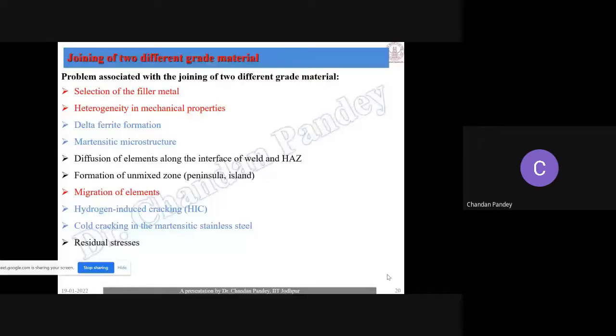But that creates a big problem. Suppose you have two materials, one is mild steel and one is austenitic steel. The composition of both is different, so it becomes very difficult to select either a matching composition with your mild steel or with your austenitic steel. That is the first thing that creates the problem, the selection of filler metal. After making a number of tests, a number of joints, and after complete characterization, metallography and mechanical characterization, we optimize the composition of the filler metal for any type of process.